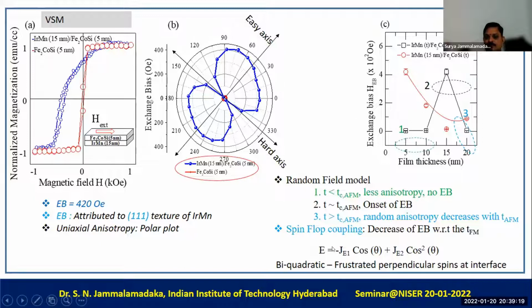Essentially, if you look at this equation, there is a linear part and there is a biquadratic part. Because of this biquadratic part, there will be frustrated perpendicular spins at the interface. As the thickness of the iridium manganese layer is more and more, the frustrated perpendicular spins at the interface will be more. So the second part of this equation will be more and more, which leads to the decrease of the exchange bias with the iridium manganese layer thickness.